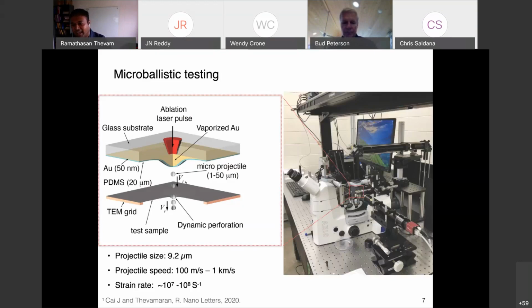This entire action happens in this microscope, as you can see over here. While doing this, we have transverse imaging at ultra-high rates, down to every 12.5 nanoseconds. And we vary the projectile velocities from 100 meters per second to 1 kilometer per second. So this gives a really good opportunity to study small-scale materials in very high strain rate regimes.